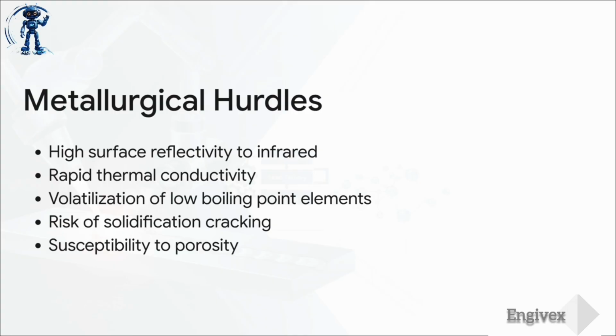And third, and this one's a huge deal, the low boiling point elements mixed into the alloy, like magnesium, will actually vaporize before the rest of the metal even melts. They essentially boil away, leaving these hollow, empty pockets behind. So when you try using traditional thermal processing parameters, this brutal combination leads to a super high risk of solidification cracking, severe porosity, and nasty blowholes. It was honestly an absolute nightmare for early engineers.